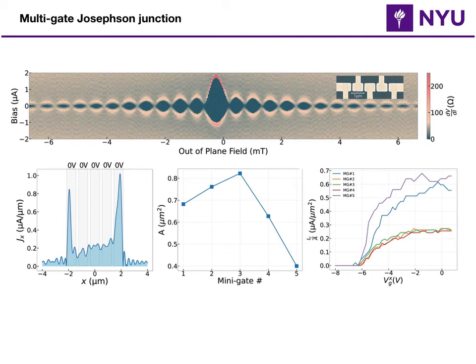You can also think that these mini gates don't have the same area coverage. So we measured the area by depleting 4 mini gates and activating just 1, doing a Fraunhofer pattern, and then from the first node estimating the area under that mini gate. Then we do the same thing for the second mini gate, right? Deplete 1, 3, 4, 5, do a Fraunhofer pattern for 2, extract the area. Once we did that, you see that the area does vary a little bit.